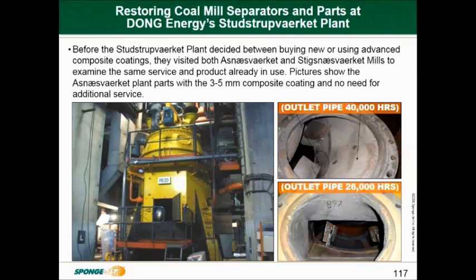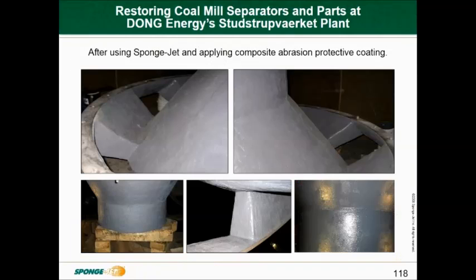After the unit had been put back into service, they checked it after 26,000 hours, checked it again after 40,000 hours, and the coating had held up. So there's a good walk-up application for most coal-fired power stations for high-build epoxy coatings. The power station now uses the same process on all high abrasion components.